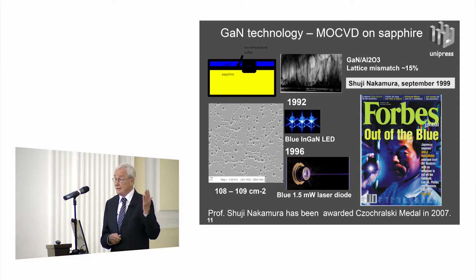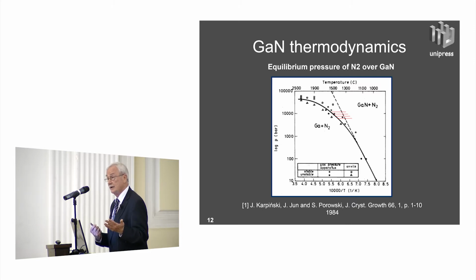However, already at this time, it was known that if gallium nitride crystals would be available, this technology would become much easier and more efficient. Everything would be more efficient, especially for lasers. At this time, we already had quite good knowledge about the basic thermodynamical properties of gallium nitride. We knew its equilibrium curve, the equilibrium pressure of nitrogen over gallium nitride as a function of temperature. This part of the picture is the part where gallium nitride is stable. Here it dissociates into gallium and nitrogen.